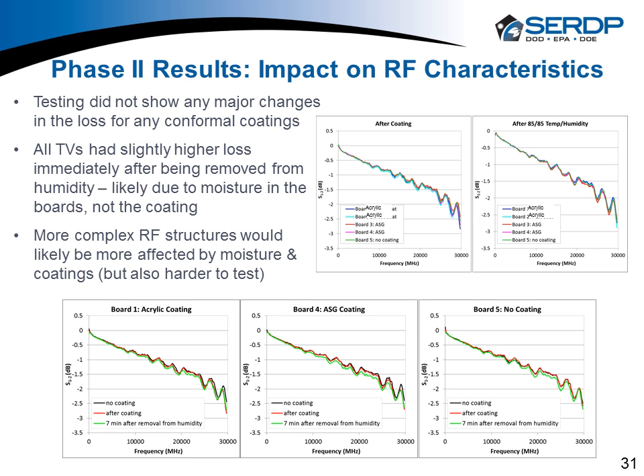We also exposed these samples to high humidity and then really quickly got them on the test rigs so that the humidity didn't evaporate off. We wanted to see if we could push humidity through. And surprisingly, whether it was before humidity or after humidity, things didn't really change, whether it was acrylic, no coating, or the ASG. So we think the RF community might have some more investigation to do in terms of coatings and what they do for their signals.